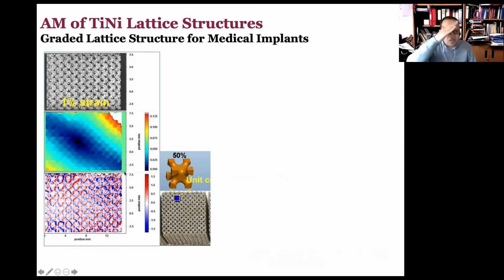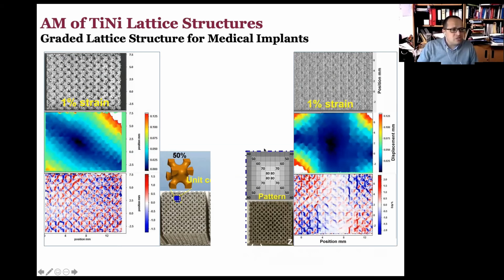So and then eventually it breaks at that direction. These are position maps measured by digital image correlation. Whereas if you are making a material where the density is changed from the outside to the inside, the part itself starts to squeeze and change its geometry, closing upon itself, similar to how those auxetic materials behave.